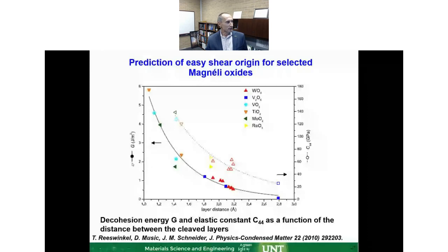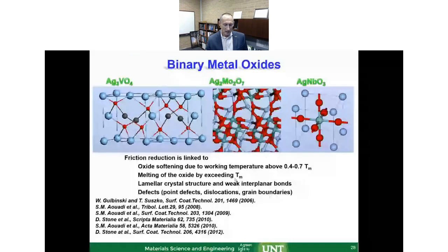The graph shows, for example, the decohesion energy and the C44, basically you think about all the shear modulus on the right, and the cohesion on the left. These are the different oxides which we ran, and the winner in terms of the lowest possible shear modulus is vanadium pentoxide. Okay, well, we already know that from the tool industry. But this showed us that yes, we can use these tools, and we can look at all other mechanisms here and predict them. And to take it further, because that was 2010, this went further, and this is work coming out of another good friend and collaborator of mine for a long time, Dr.